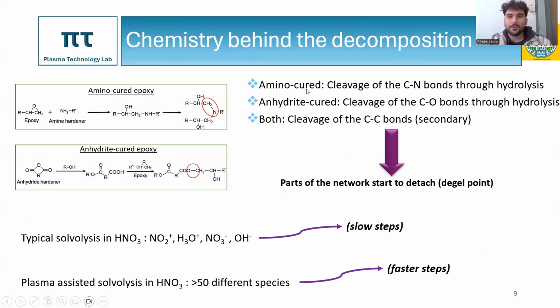For example, the amino-cured network can be decomposed due to cleavage of its carbon-nitrogen bonds, while the anhydride-cured network due to cleavage of its carbon-oxygen bonds. When enough bonds of the network have been cleaved, then parts of the network start to detach, and this is what we call the D-gel point.